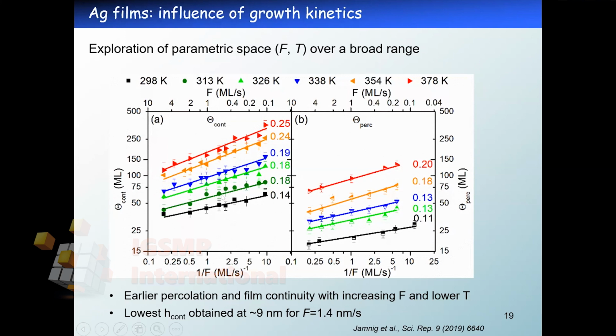And for all the investigated temperature, in the log scale, we can obtain this linear behavior, which gives us some information on the underlying atomistic mechanism that govern the formation of the growth. And typically, we can extract here some information about the activation energy for diffusion, for instance.